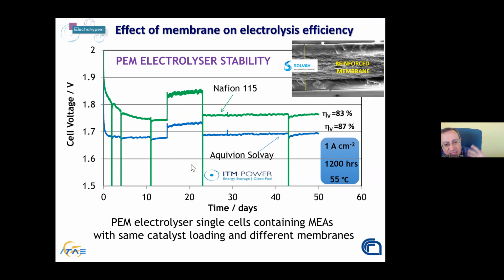Our colleagues at ITM Power in the UK showed, using a parallel experiment with two plants running on the same feed water to avoid interference from other effects, that the Aquivion short side chain membrane shows much better efficiency: 87% voltage efficiency compared to 83% voltage efficiency of Nafion.